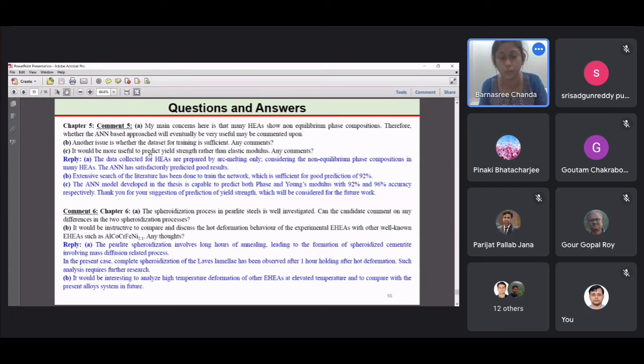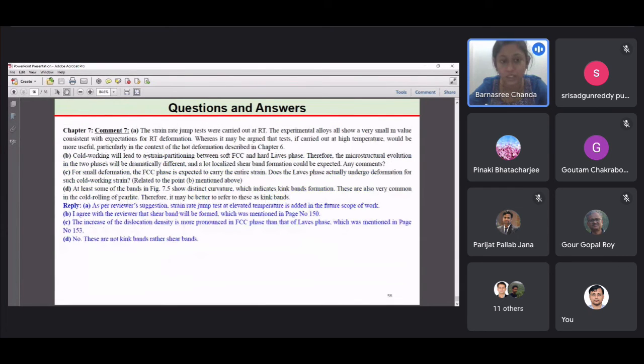But as per your suggestion, chapter 7, strain rate jump test carried out at room temperature, the experimental alloys all show a very small m value consistent with expectations of room temperature deformation. Whereas it may be that the test, if carried out at high temperature, would be more useful, particularly in context of hot deformation. Yes, as per your suggestions, we have taken this as our future work.